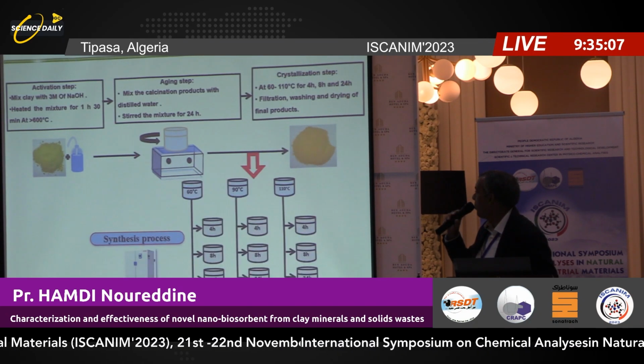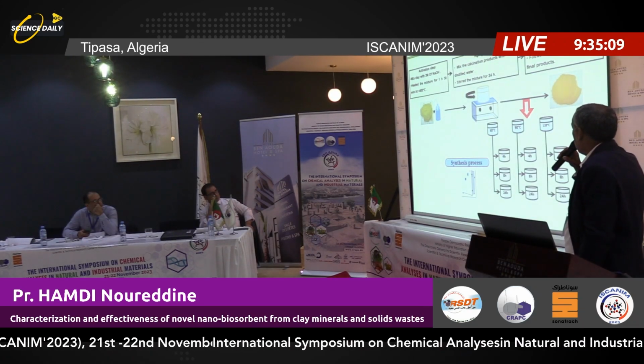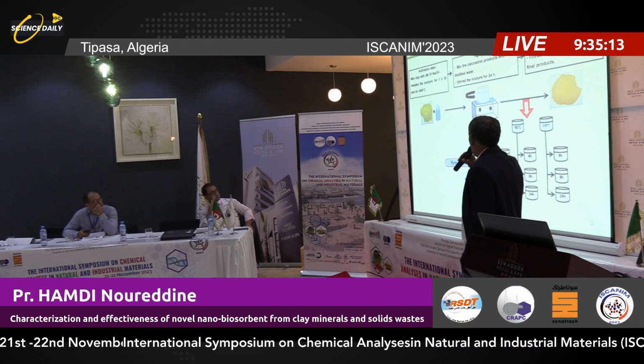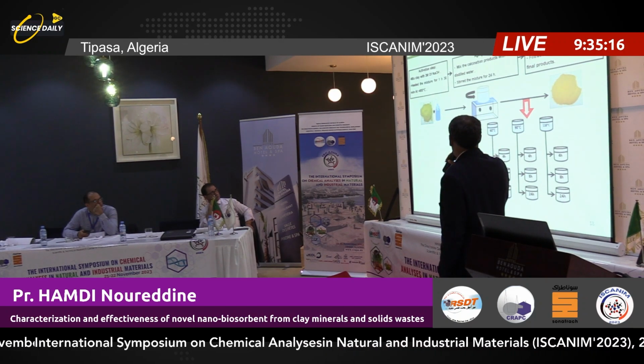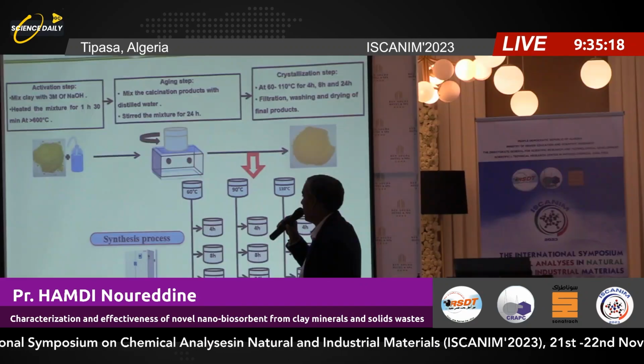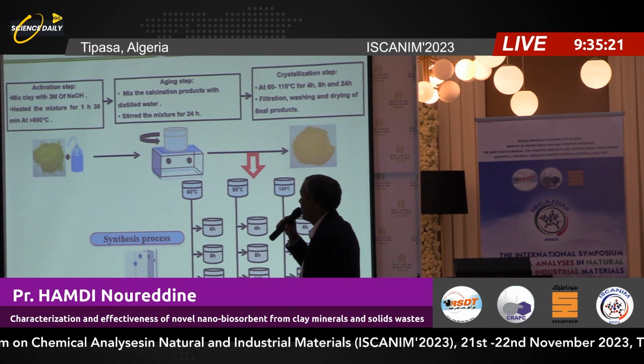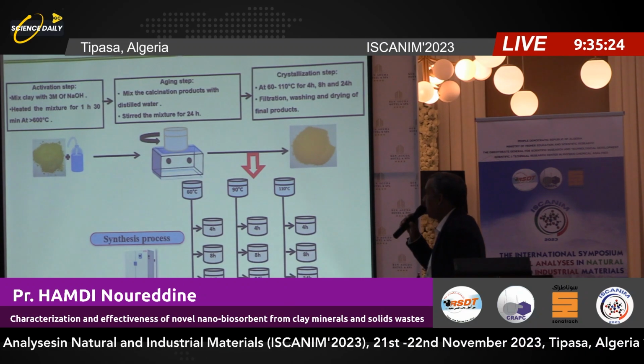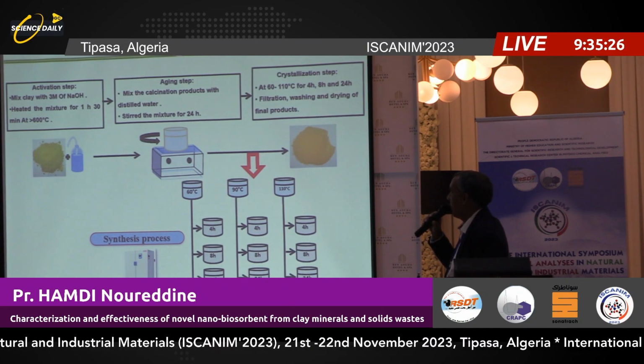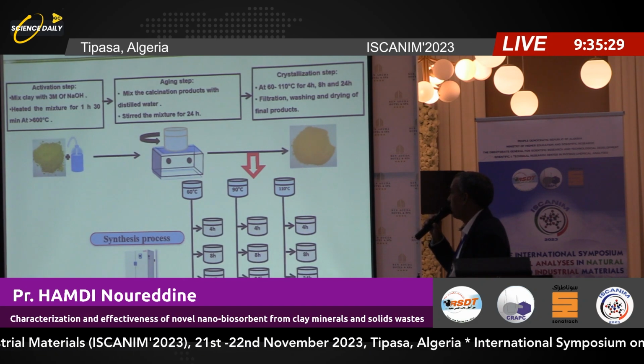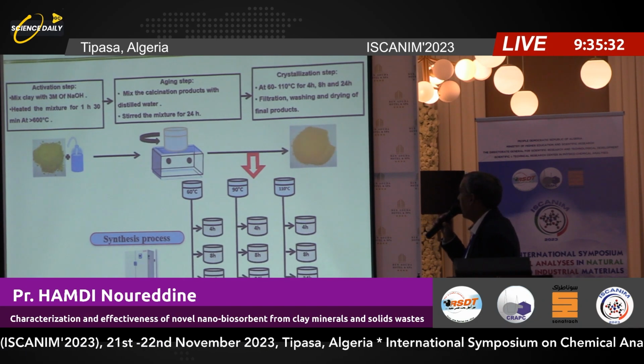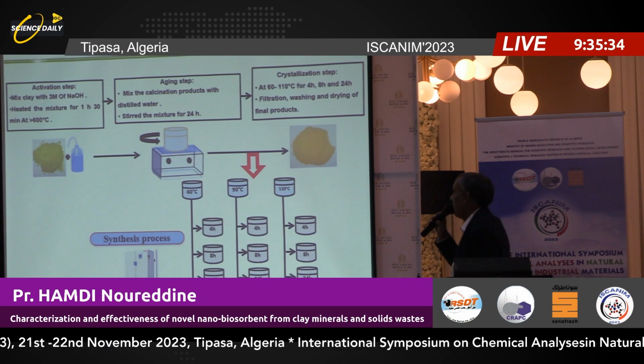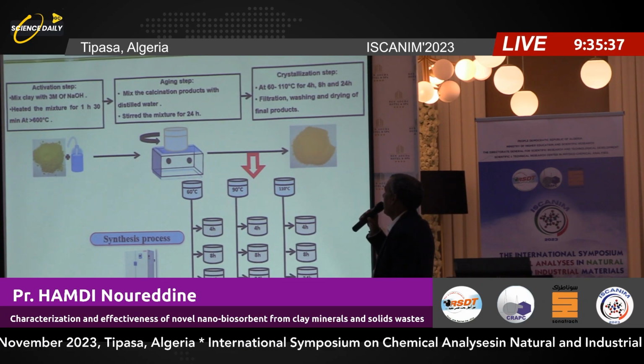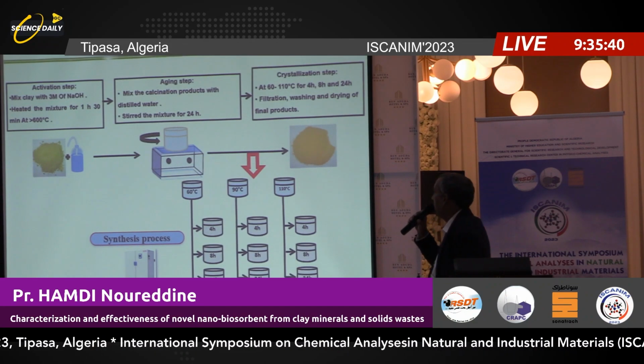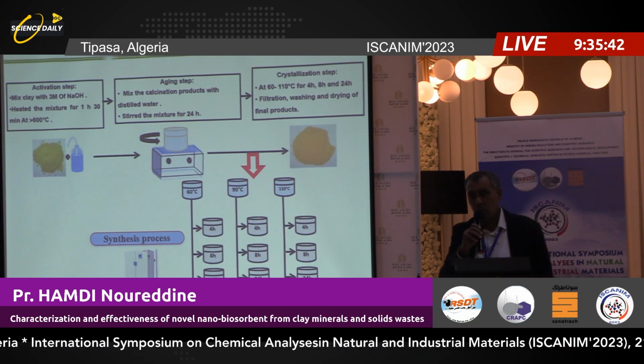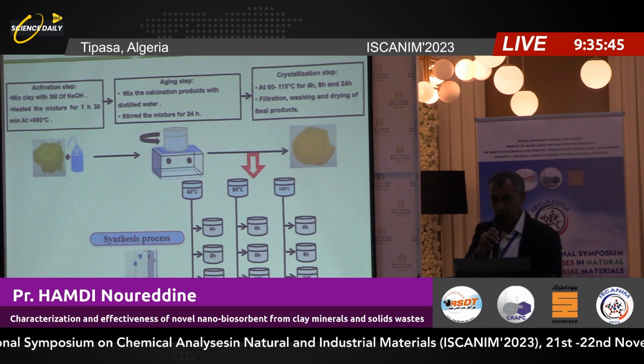Now I move to the preparation of the zeolite. We mixed the clay mineral with 3 molar sodium hydroxide and put it in the furnace at a temperature of more than 600 degrees C for 1 hour and a half. After that, the aging step is the mixing with distilled water for 24 hours, and the activation or the crystallization can be at different temperatures, 60 degrees C to 110 degrees C. And after that, the composition can be filtered and dried.